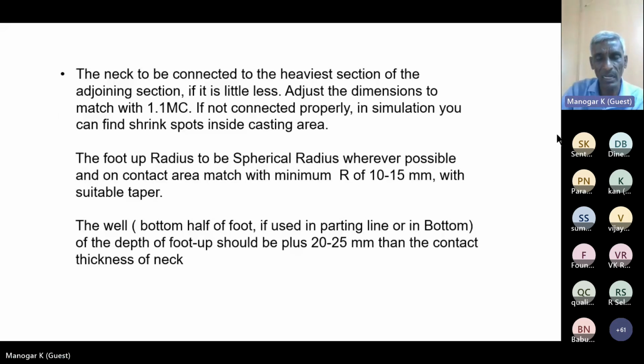The foot pad radius should be a spherical radius. Normally I see in foundries they are not keeping the spherical radius for the bottom side of the foot pad. It is better to have it so that it has a better surface area and improves the yield. And also it should have a well base. This is also not followed in many foundries. They simply keep a flat base. It is suggested to use a spherical base.